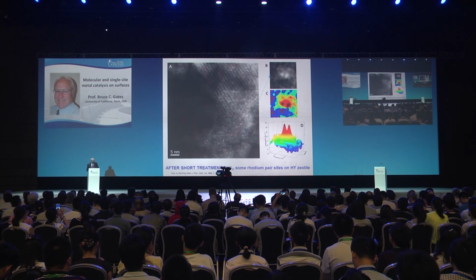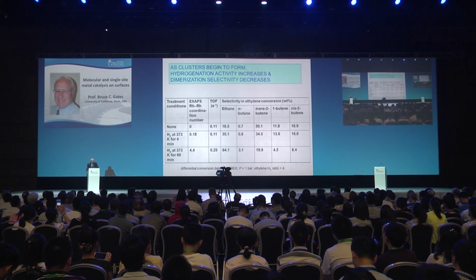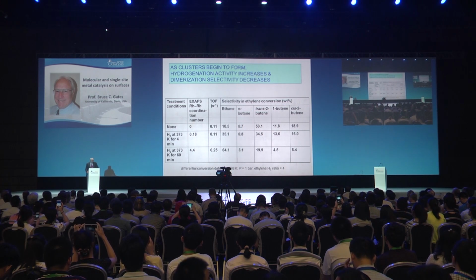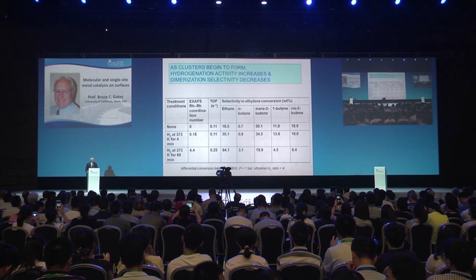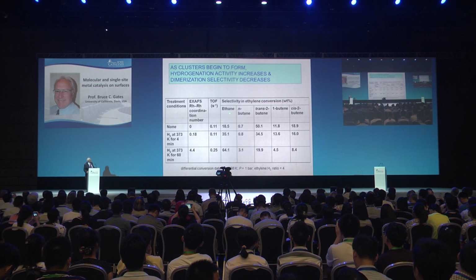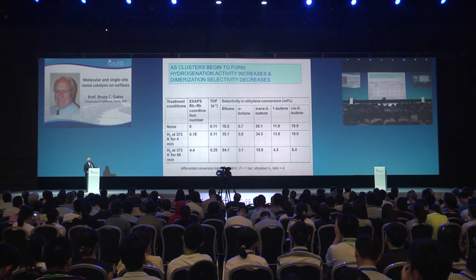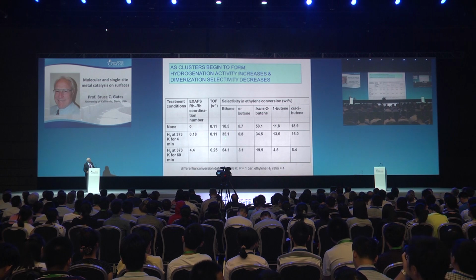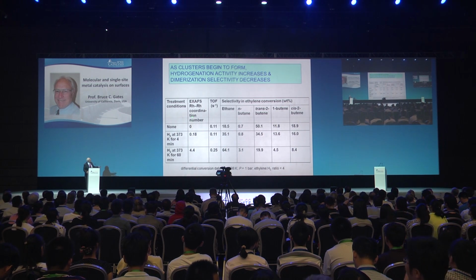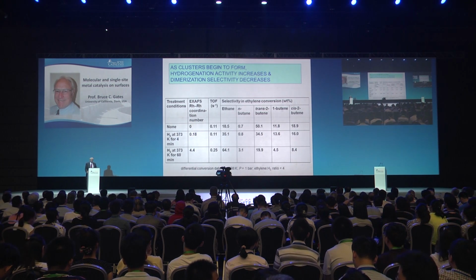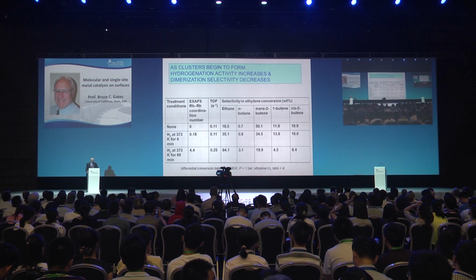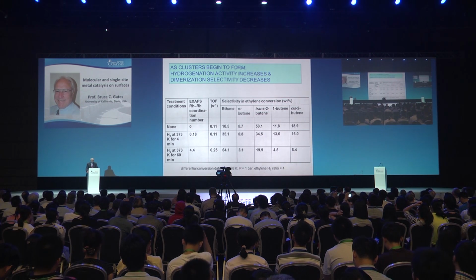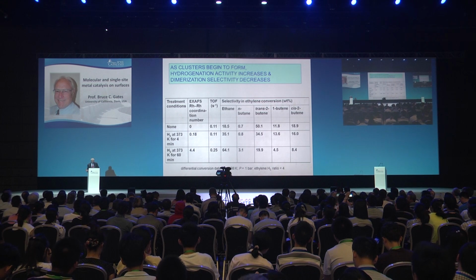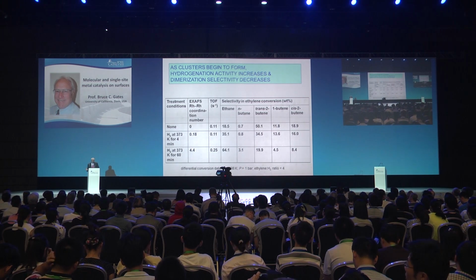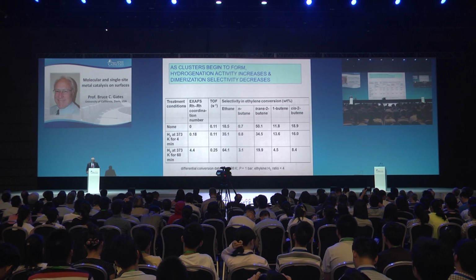What happens in the catalysis? Well, of course it changes. Let's look at the selectivity for ethylene conversion with hydrogen. The ethane formation rate is increasing as we increase the rhodium-rhodium coordination number, as we're forming the smallest clusters and then bigger clusters. So the catalyst is getting more like a conventional supported rhodium metal catalyst, and it's a better hydrogenation catalyst.